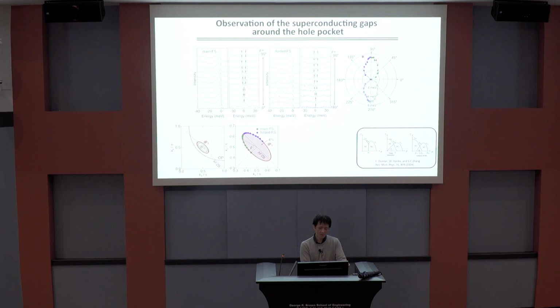And also, you would be interested in the superconducting gap, which I show here. I plot the original curve and the symmetrical curve to show the gap opening around this hole pocket. And we clearly see the gap opening if you go from the nodal direction to the edge of this pocket. And I plot here the size in polar coordinates.